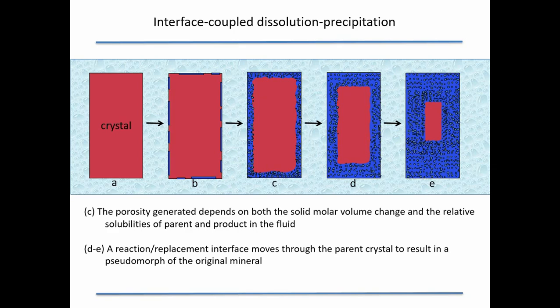And the best way of doing this is with isotopic tracing, and I failed to tell you that with the original experiments all those years ago, we enriched the potassium chloride solution with potassium 40. So we knew that the potassium from the solution ended up in the new solid phase, just as the oxygen from the solution in the plagioclase experiments ended up in the aluminosilicate structure of the new phase.